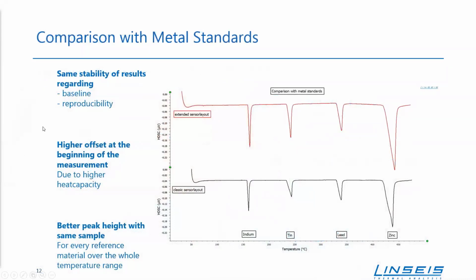Okay. First of all, of course, we have to do a calibration. We want to compare the reproducibility, and what I can say is they are comparable. The shape of the baseline is basically the same. So all of our software corrections and so on still work. What's the matter for this? Convection and the heat radiation are still the same, because the shape of the sample and the reference site is still the same, and also the size of the reference below the sensor and the size of the ceramic above the sample sensor is the same. So this works perfectly here.